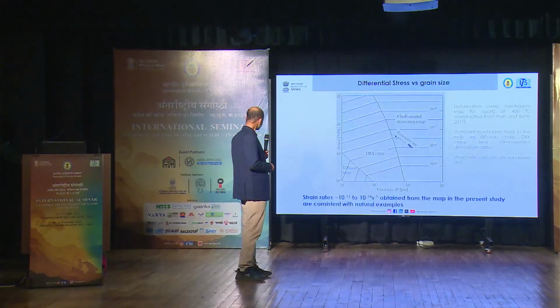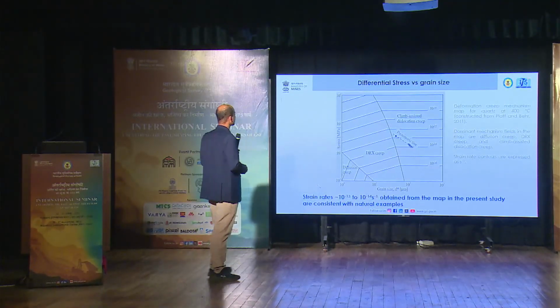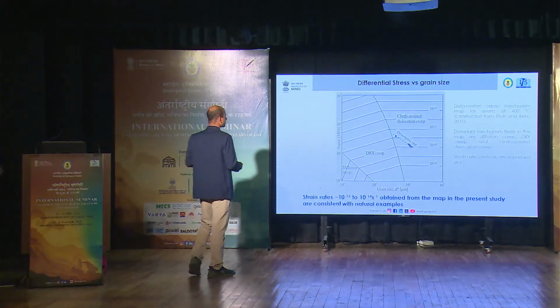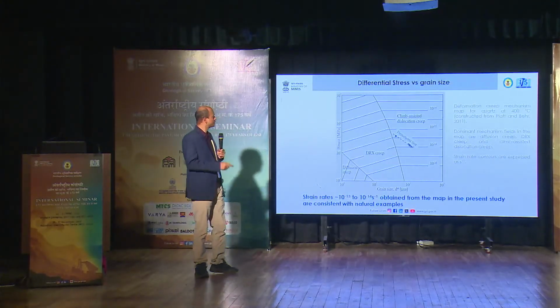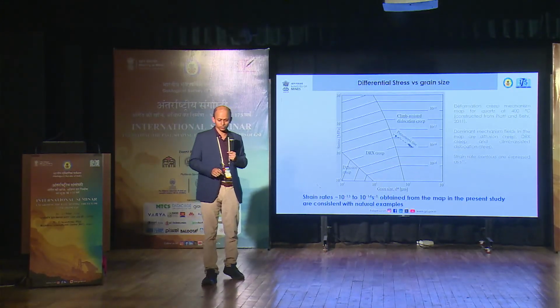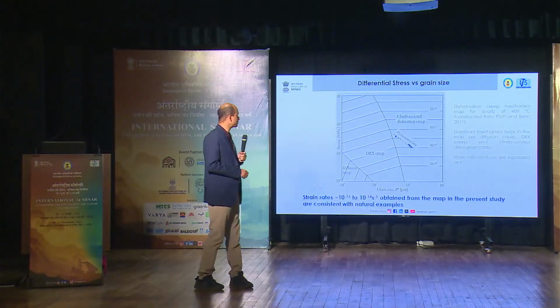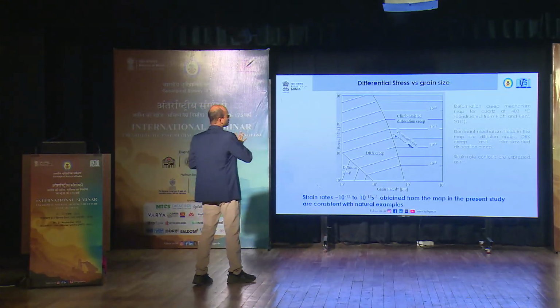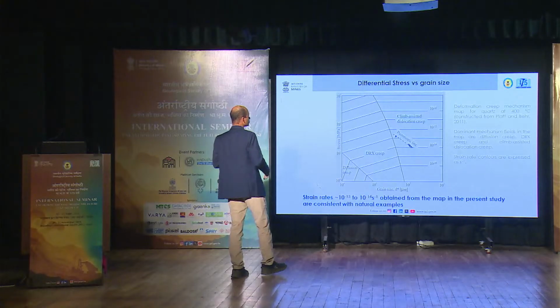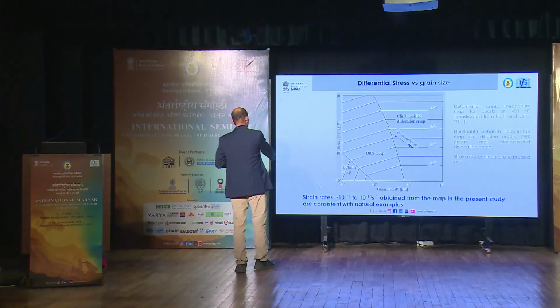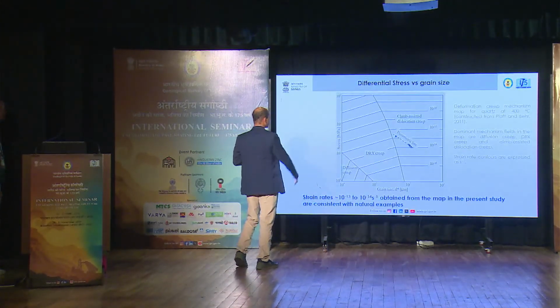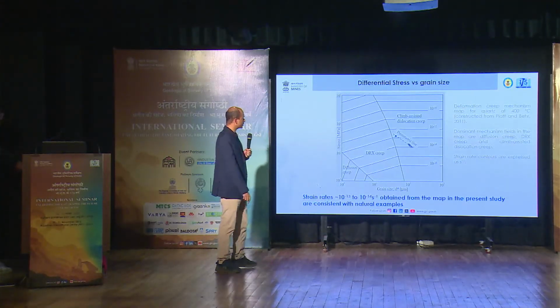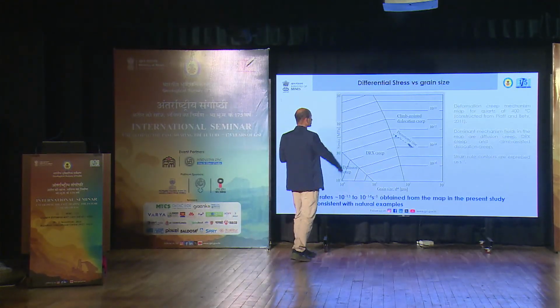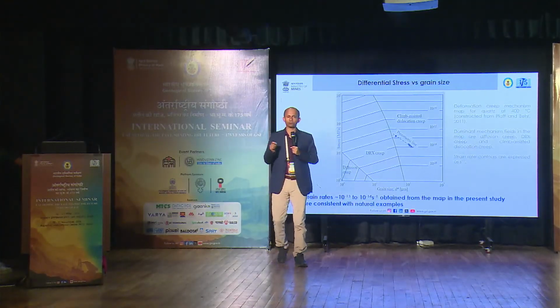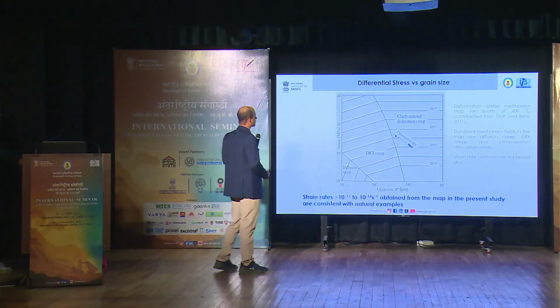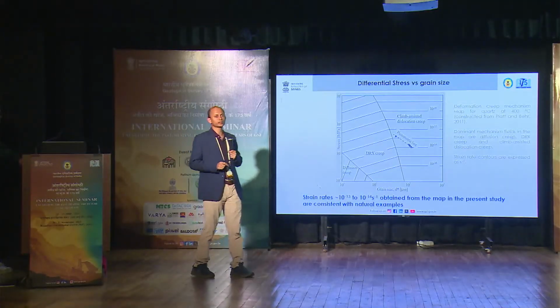Next. Now we have plotted the differential stress and the grain size in a deformation creep mechanism map. This deformation creep mechanism map was constructed by Platt and Behr 2011, and this is valid for around 400 degrees centigrade and above. The dominant mechanisms fields are diffusion creep, DRX creep, and climb assisted dislocation creep, and we have the strain rate contours here. These are 10 to the power minus 10, 10 to the power minus 12, and these are in per second.